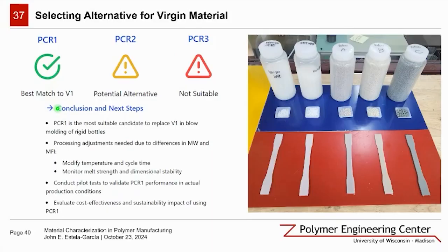Additionally, it didn't actually meet the standard MFI benchmark for blow molding. So that means that we're going to have to change some of our processing parameters. So we're going to have to adjust our process to successfully integrate PCR1. This can include modifying temperature profiles or modifying our cycle times. Close monitoring of the melt strength and dimensional stability is crucial for the transition to this material, along with pilot tests to validate the performance under actual product conditions.